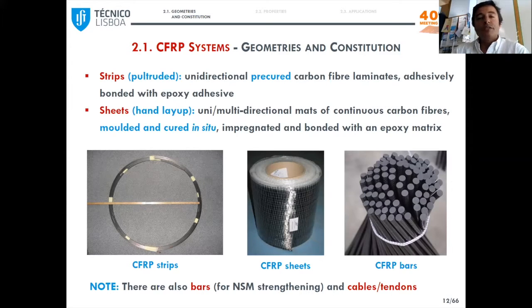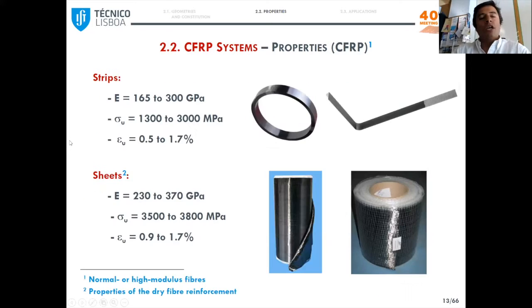They are already precured and are simply bonded to the substrate of the member that we want to strengthen with epoxy adhesive. And then sheets with uni or multidirectional mats, which are molded and cured in situ, so applied by hand layup, being impregnated and bonded with epoxy resin. Here you can see some typical ranges of variation of mechanical properties of these CFRP materials. You can see that the modulus is roughly similar to steel, structural steel, while the tensile strength is about 10 times higher in components that are, of course, extremely lightweight.